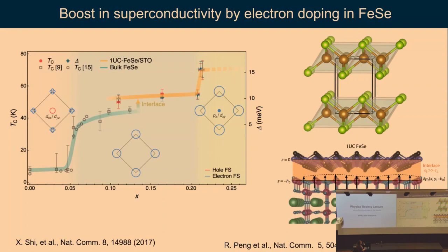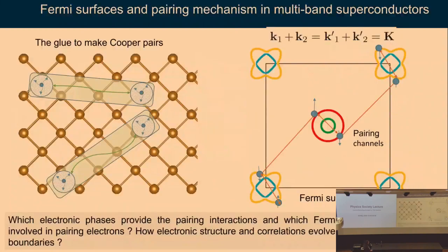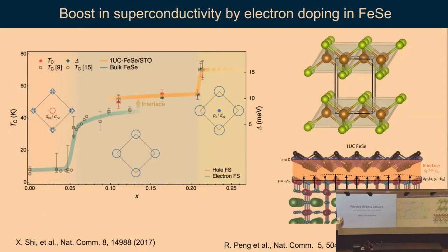And one can also dope the materials. What I showed you in the substitutional graph earlier, selenium, tellurium, and sulfur are in the same periodic group. So if you exchange them, you do not add extra electrons. You just change the sizes. But you can add other elements that can dope the system, or you can intercalate between the layers. You can put some potassium in, and then you can enhance superconductivity by giving the system lots and lots of electrons. And as a result, these pictures here are slices of Fermi surfaces.